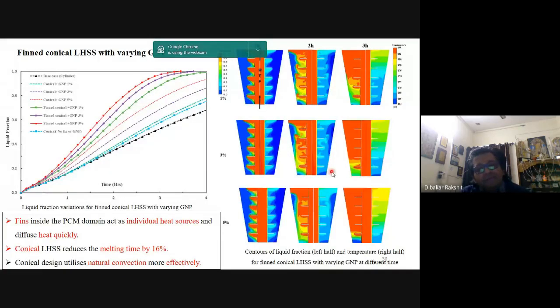Again, the same attempt was done for the CFD analysis by mixing the graphene nanoplates at 1%, 3%, and 5% by volume for this conical type of thermal battery. And these were some of the observations which we found: fins inside the phase change material domain act as an individual heat source, which we found in our previous study also for the cylindrical type of thermal energy storage battery. But here, although it becomes a heat source, because of the conical shape it diffuses the heat very quickly. This was quite interesting and on the positive side of changing the shape. And this conical structured latent heat energy storage system reduces the melting time by more than 16% compared to its cylindrical counterpart.